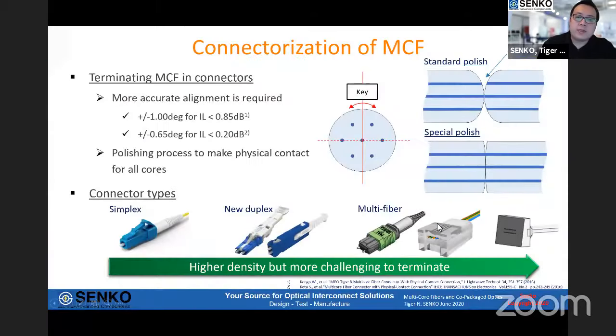And going next, when it comes to connectivity of the multi-core fibers, of course, as you can imagine, the accuracy of the fiber alignment is very, very key. It's similar to PM fiber alignment, but it's more challenging because you have 7 different cores in this case to align to the opposing fiber or connector. So it's really challenging. And some of the papers I referenced say that if we can align within 1 degree, we can achieve insertion loss of 0.85. If it's 0.65 degrees, it's going to be 0.2 dB.